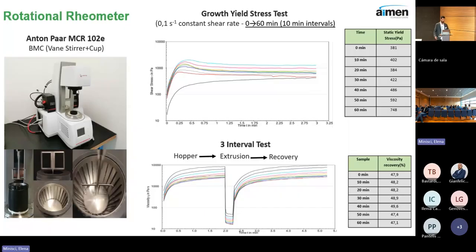And we complement these characterization techniques with more complex rheology using a rotational rheometer. It's the same that Ricardo saw before, but we have changeable geometries, and we use one geometry suitable for building materials, which is called a BMC. That is basically a vane stirrer within a cup. We fill it with our sample, and with this equipment, we can carry out complex rheology. I can highlight two important tests.